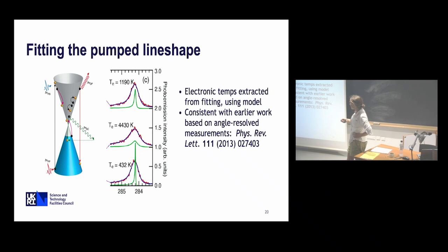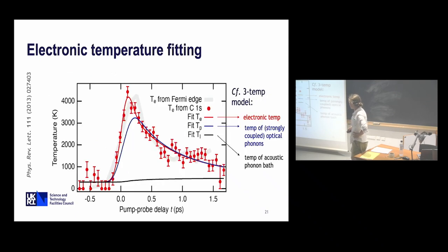And then we have strong coupling to optical phonons in the system, which gives a relatively quick decay, or let's say reduction, in the temperature of the excited state electron population. And then at some point, we have a bottlenecking effect and a subsequent very slow decay, wherein there need to be supercollision events or coupling to acoustic phonons, which is a very slow process.